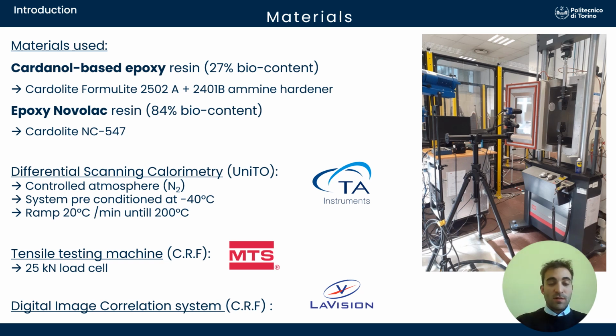Then the differential scanning calorimetry tests were performed by Università di Studi Torino using a TA instrument working in controlled atmosphere of nitrogen, performing a curing ramp of 20 degrees Celsius per minute until 200 degrees Celsius, starting from minus 40 degrees Celsius. From the laboratories of Centro Ricerche Fiat, we performed the tensile test by means of an MTS tensile testing machine provided with a 25 kilonewton load cell and with a digital image correlation system from LaVision.